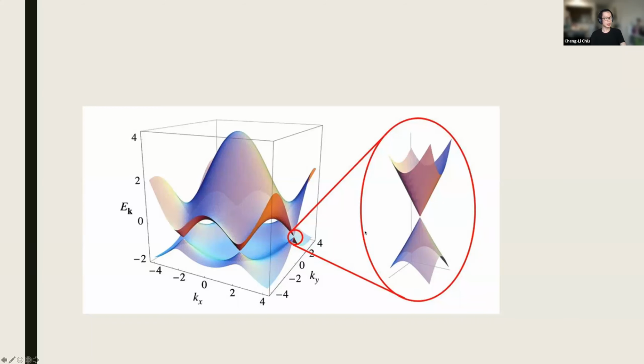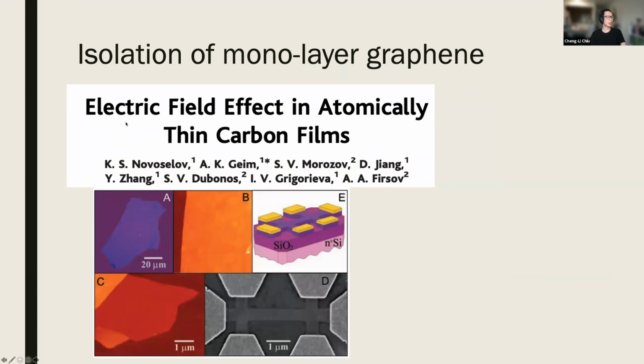And this material is amazingly easy to get, actually. This is the original paper that helped the people get a Nobel Prize. They successfully exfoliated graphene. If you stack a lot of graphene together, it becomes graphite. And people have been using graphite for, I don't know, 1,000 years, because it's just your pencil. However, getting only a single layer of graphene from graphite is something that people never thought possible. However, people found that it's actually easier than they thought. You just need to take a tape and put graphite in between, and when you split the tape, the graphite becomes two. If you keep doing this, you can thin down your graphite, and eventually it becomes a monolayer.